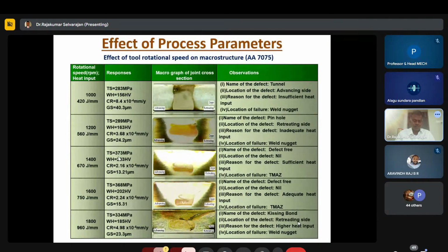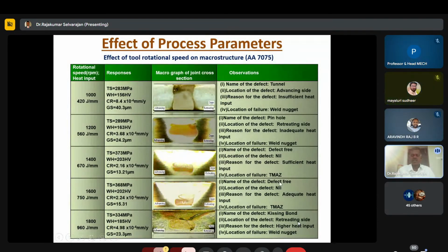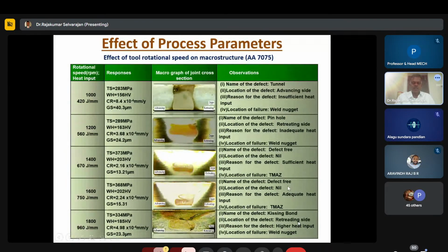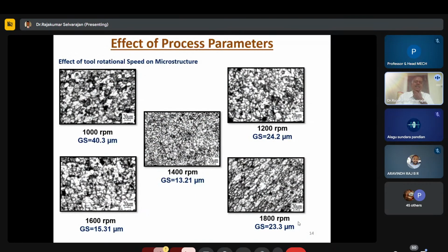We can obtain 368 megapascal, and 1600 RPM is also a defect free joint, but the failure is in the TMAZ region. You can see the corrosion rate is higher at 1600 RPM when compared with 1400 RPM. Beyond that, at 1800 RPM the strength is lower because of the higher heat input. It ends up with kissing bond defects on the retreating side, mainly in the weld nugget area, the center of the weld. So we can conclude that 1400 RPM is suitable for this 7075 aluminum alloy.